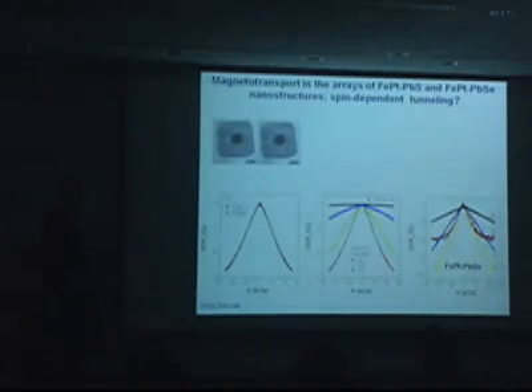And it looks like the mechanism of how it affects is determined by so-called spin-dependent tunneling. The idea is that the tunneling rate depends on the orientation of spins of electrons before tunneling and after tunneling. It can be understood as in classical spin-dependent tunneling, or tunneling magnetoresistance, or GMR heads, giant magnetoresistance heads or magnetic tunneling junctions. It is described by the difference in the density of electronic states at the Fermi level for spin up and spin down configurations.